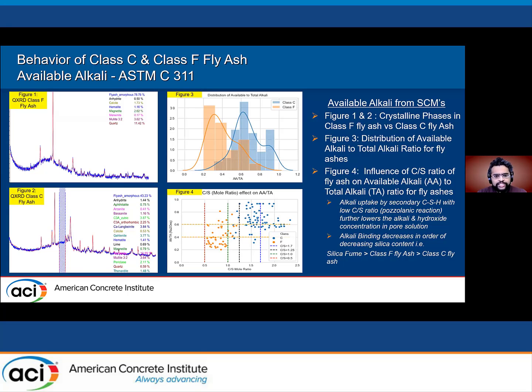And the fourth important aspect that we also need to consider with the SCMs is that these SCMs add silica, or amorphous silica. So as the silica content increases, the C to S ratio in the overall hydrated phase, or the CSH, decreases. At the lower CSH or C to S ratio, it has the capacity to bind alkali and further lower the pore solution concentration.